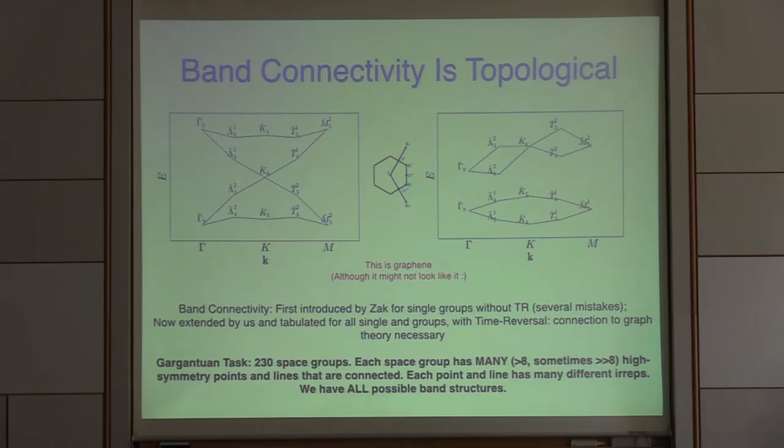For example, graphene, without having PZ orbitals, if I just go into the SP hybridized bands, if I somehow could tune my Fermi level there, those bands would also have to be topological. So basically, on the graphene lattice with the atoms sitting here, all the bands have to be topological, all types of orbitals, not only the PZ orbitals. Bismuth square nets are another example, where if I choose my bismuth to sit at some position in the unit cell, and I'll tell you about it, the bands have to be topological.